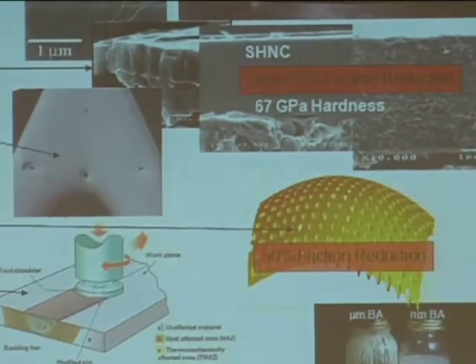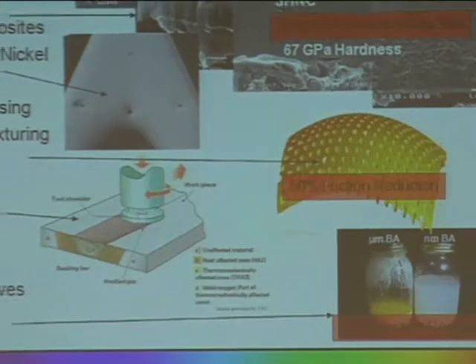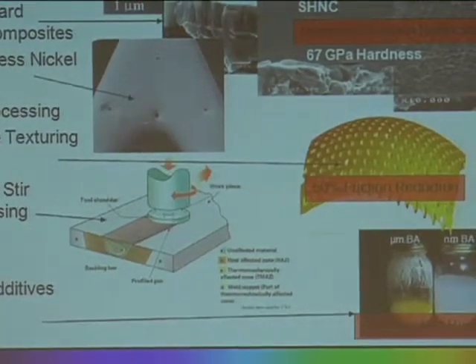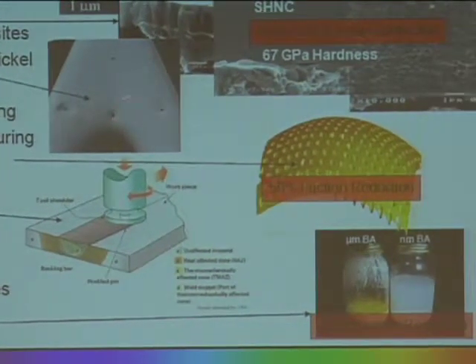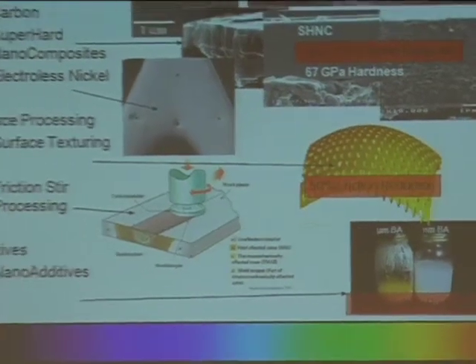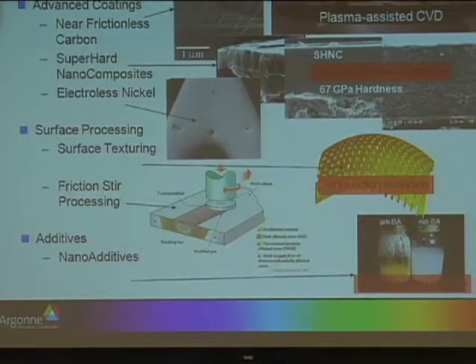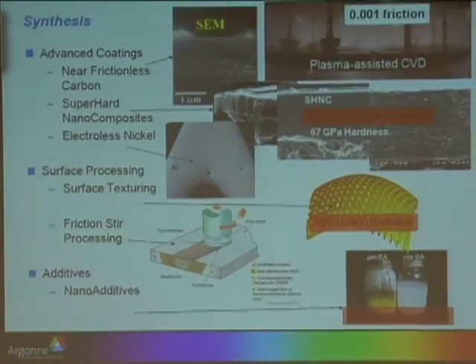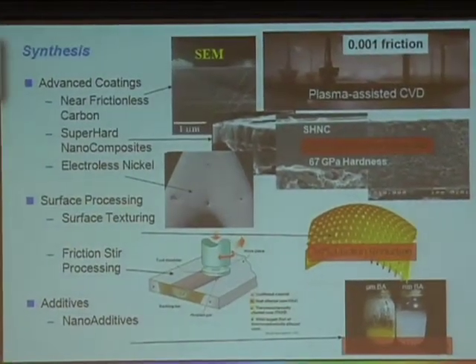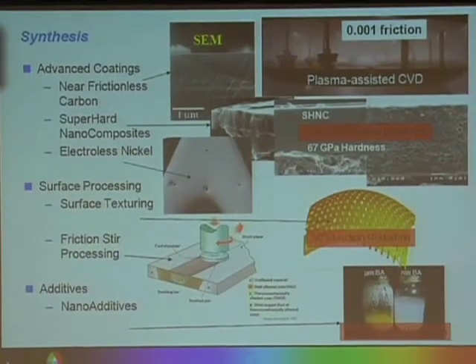We also have a process where it's not necessarily a tribological process, but it's an electroless nickel process that's being used to fabricate very small orifices for our diesel fuel injectors. We can produce orifices that are quite long, but are quite small in size, down around 50 microns in diameter.